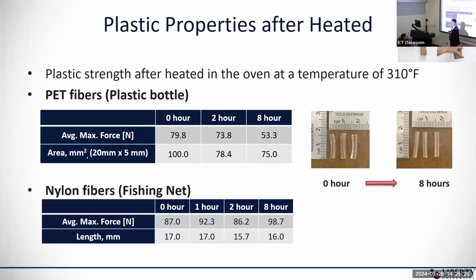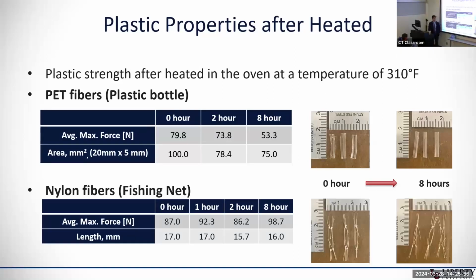The reason why we did this is to see how the surface area changes over time, because it actually determines the content of the asphalt binder. If we have a larger contact area, we need more binder. As you can see here, the area also reduced by 25% after 8 hours. Then we put the nylon fibers, which are from the fishing net, into the oven. But this nylon didn't change its properties in terms of maximum force, and the length also didn't change much over the hours.